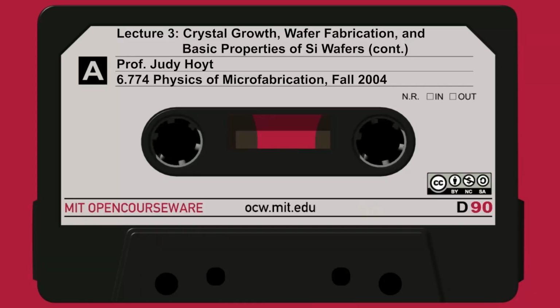The exact same thing applies here. This is the concentration of electrons, and this is instead the concentration of these charged vacancies, which obeys a very similar relationship. So in equilibrium, the concentration of CV plus, the single positively charged vacancies, depends on the concentration of neutral vacancies. The pre-exponential is the neutral concentration, times the exponential of the distance between EV plus and the Fermi level over KT.